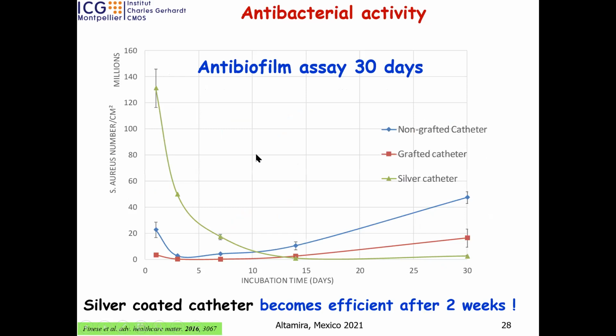What about biological properties? Okay, we compared our grafted catheter in red here and an ungrafted one, as received, without any antimicrobial property, and we compare it with a silver catheter. It's an antimicrobial, antibiofilm catheter that you can buy in the pharmacy also. And what we observe, interesting thing, is that our catheter here, even after a few hours, 12 hours, I think, it is 1 day here. So after 1 day, we can say there is no biofilm on the surface by comparison to the untreated one, and surprisingly, the commercial one has a very huge number of Staphylococcus. There is a lot of development.